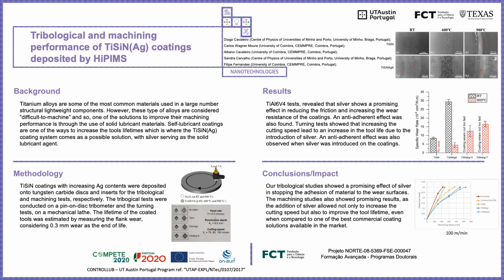As for the results, starting with the tribological tests against alumina balls, we can see on the graph here that for room temperature tests, the addition of silver actually deteriorates the wear resistance of the coatings. However, when the temperature increases to 600 degrees C, we can see a general increase in the wear resistance of all the coatings when they're compared to their respective room temperature counterparts. As for the tests against titanium aluminum 6 vanadium 4 balls, we found that the addition of silver coupled with the increase in temperature increases the wear resistance in a general manner.